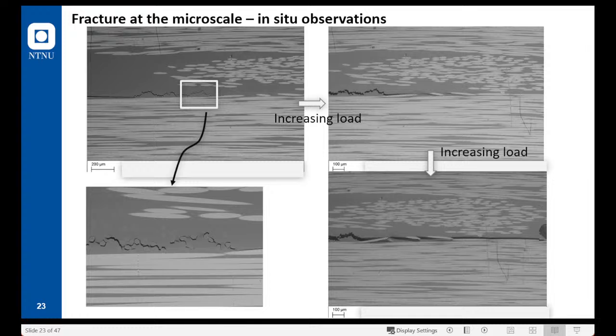Also from this figure, we can see that although we talk about unidirectional composites, the actual microstructure is a lot more complicated because we have the support threads. These are the UD fibers. This is the support thread. These are the stitching yarns, where the crack actually goes around the stitching yarns, and this is a resin-rich area. By doing such an experiment, we can understand how damage starts to initiate at the micro scale, and eventually it will evolve into a crack at a higher scale, in the meso scale and at the component level.